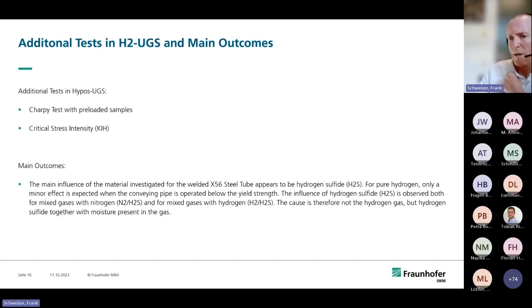If you have only pure hydrogen and no H2S, there's a minor effect expected when the pipe is operated below the yield strength. Above yield strength, you get micro cracks, and as I showed, the hydrogen will pronounce the crack propagation. And we tested, as you saw, the influence of hydrogen sulfide with mixed gases, with nitrogen and with hydrogen. This means the hydrogen gas and H2S mixture is not relevant for the crack propagation. The H2S together with moisture is the main thing you have to look for.